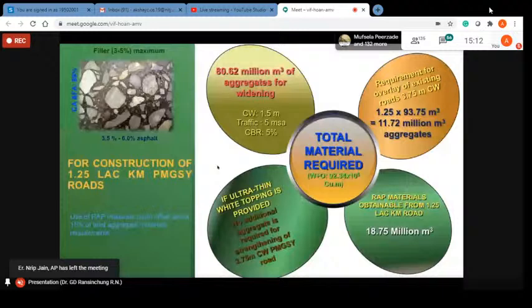That's it. Then, what are the challenges that we are still facing today, despite having some preliminary and well-established guidelines for the use of RAP materials in formulations of the bituminous mix? I would like to point out 2-3 points. As per MoRTH Clause 519.2.5, when the amount of RAP to be used in the bituminous mixture exceeds 10%, the penetration value of the recovered binder from the reclaimed material before mixing should exceed 15 penetration value. Again, from the available literature, the current agency specification typically indicates 15% RAP. And then, when the RAP content in a mix is between 15 to 25% by weight.